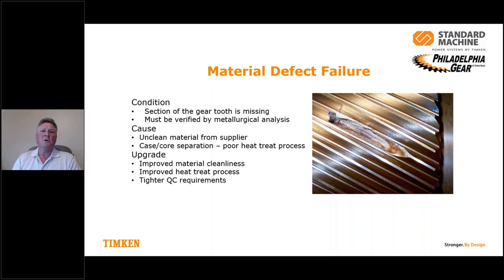The best way to find out what's causing that is to do an analysis, a metallurgical analysis. You need to look at it under a higher power microscope and find out what is actually happening to the material. As I said, unclean material is a cause, but it's becoming less of a cause. One of the things that we do see is case core separation. So when you're carburizing a gear tooth, you're penetrating the carbon to a certain case depth. But if the heat treat process isn't done correctly, then you'll have a potential for separation between the soft material and the hard material. And when that happens, it's usually a dramatic failure, such as what you see on this picture. So tighter quality control requirements and improved heat treat processes are usually the upgrade or the way to stop this type of failure.